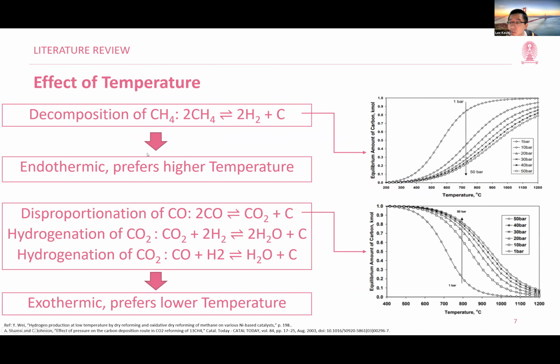So the effects of temperature are normally split into two sections, endothermic and exothermic. The four equations that we've seen just now, we split into both. Endothermic prefers high temperature. You can see on the graph here, higher temperature means higher formation of coke, and for exothermic, lower temperature means higher carbon deposition. So if we were to adjust our temperature to a slightly higher temperature, we can actually eliminate all three of these equations and only focus on one.